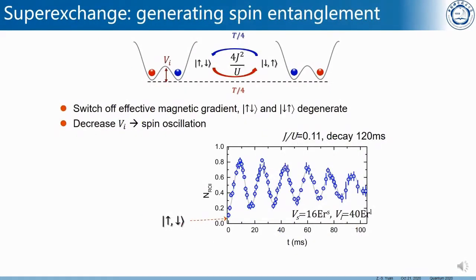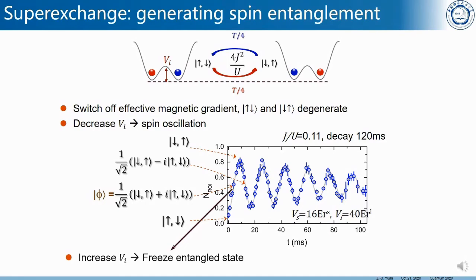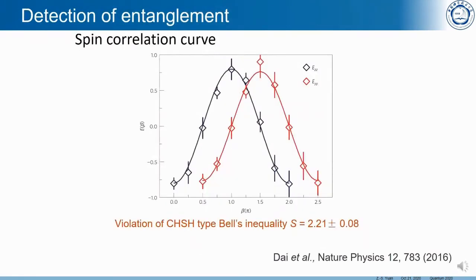After we prepare the initial state, we can lower the potential barrier in the middle to let the system evolve under the driving of the super exchange interaction. We then stop the evolution by ramping up the barrier again at a proper time for achieving a desired entangled state. When we have the entangled state, we measure the spin correlation curve, and finally, we observe the violation of Bell's inequality.